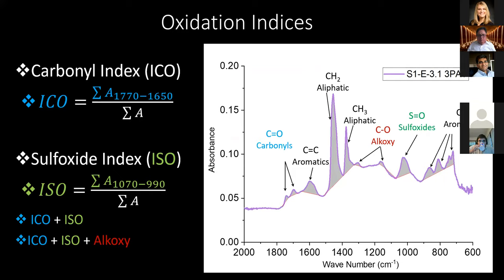Specifically, the oxidation indices that are most relevant to the binder modification study are the carbonyl index and the sulfoxide index. If we sum the area under the peaks in the appropriate ranges and divide by the total peak area, the indices can be quantified and compared to determine the oxidation or aging of the modified binders.